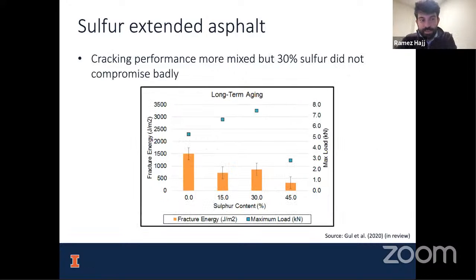Well, we saw more mixed performance, to be honest. In 0%, we did see the highest fracture energy, which means it takes the most energy to fracture the mix. So we did see that the non-sulfur mix is performing a little better, but the peak load of the 30% sulfur was the highest. And this is important because the fracture energy is how much energy it takes to fracture the mix, meaning how much it can deform and strength combined. The maximum load is just the pure strength of the mix. So we did find better strength, but a little bit worse fracture energy when we use 30%.